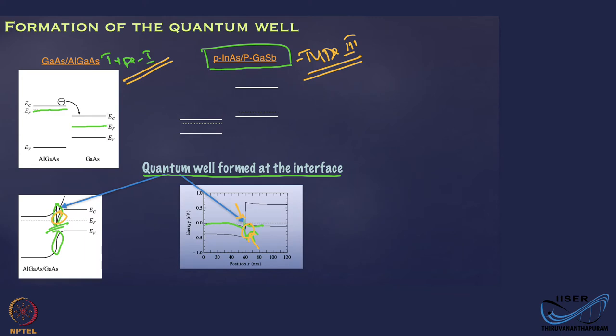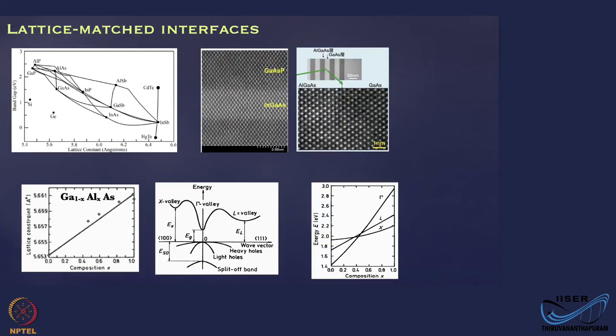As you have seen in the previous slide, your charge carriers end up in this well, either here or here or here, which is right at the interface. So the quality of this interface is probably the most important thing when we consider these material systems, because that is where all the movement of charge carriers is going to take place. That is where these charge carriers are going to end up. So how good, how crystalline, how perfect this interface is, is of paramount importance. For that, what we need from the solid state physics point of view is a perfect lattice matching. When I say perfect lattice matching, it means there are no defects or dislocations at the interface.